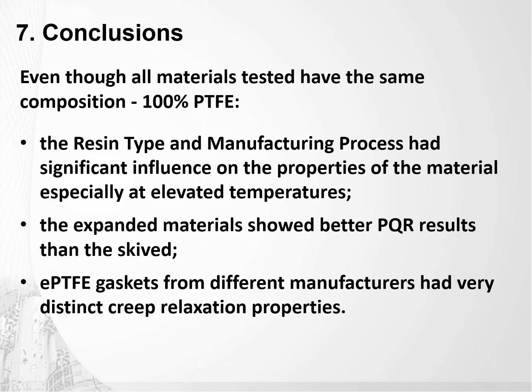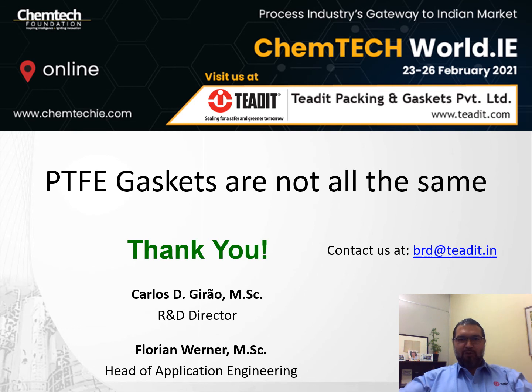Going to our conclusions: even though all materials tested have the same composition — 100% PTFE — the resin type and the manufacturing process had significant influence on the properties of the material, especially at elevated temperatures. The expanded material showed better PQR results than any skived tested, and the ePTFE gaskets from different manufacturers had very distinct creep relaxation properties. I hope you enjoyed the presentation and thank you for your time. If you have any queries, please don't hesitate to contact us.